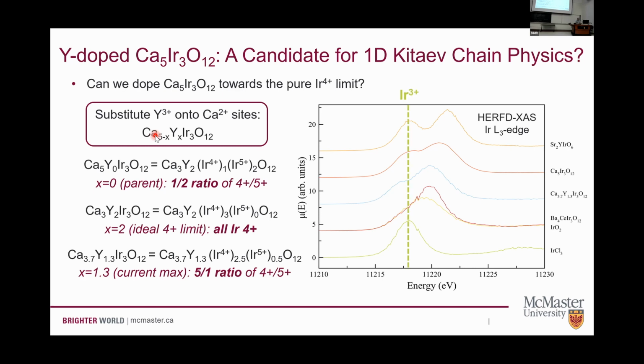What we can do is compare to these reference materials, and the position of these absorption features is very sensitive to the oxidation state. So you can see that there's about a 1 electron volt shift as you go from the iridium 3+ to 4+ to 5+ oxidation states. You can see our 5,3,12 parent compound sitting in here, about 2/3 of the way between 4+ and 5+. And you can see that the 1.3 sample is quite close actually to this iridium 4+ line here. Okay, so this is a good sign that we're getting close to the limit that we're interested in.